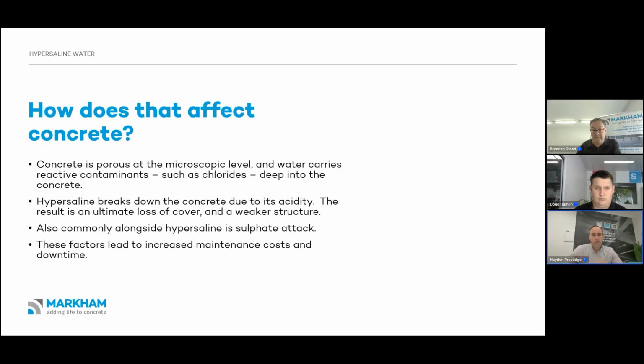Now, as you lose cover on the concrete surface, it just becomes more and more porous, allowing more contaminants to get through to the depth of the steel. We see things like expansion, cracking, spalling, breakouts, all stemming from this environment. It really breaks down the strength. The acidity starts eating away at the concrete, and then along with that you get sulfate attacks, which lead to that expansion, cracking, etc.